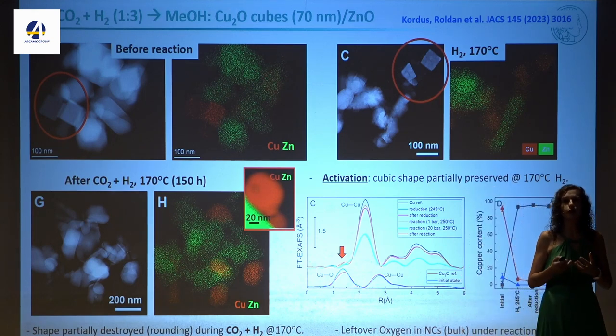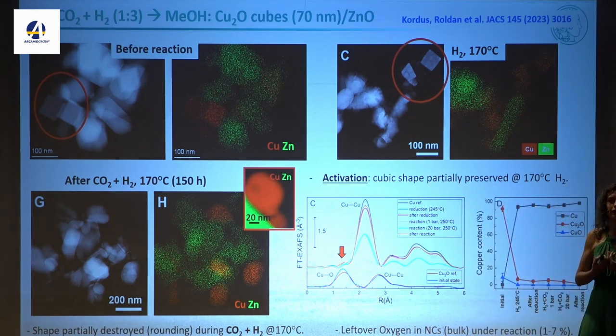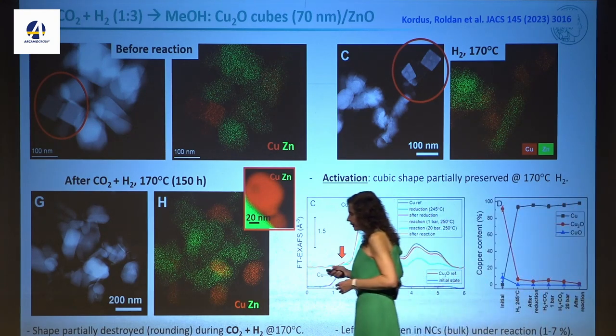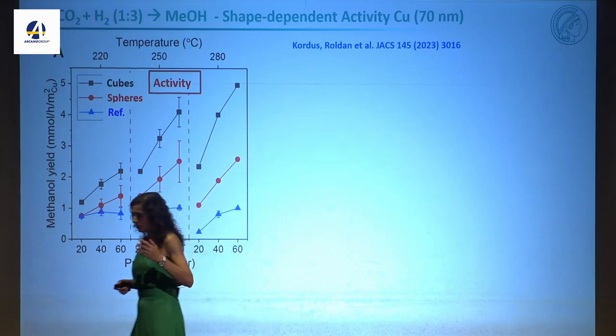And we believe this is good, because this also helps us to minimize the brass formation, which is actually leading to the activation. We can also follow these different species, and you can see here under reaction conditions, the signal of Cu2O was decreasing, and then you never go to completely zero. You keep between 1% and 7% of this oxygen in these structures. So now we'll look at the reactivity.